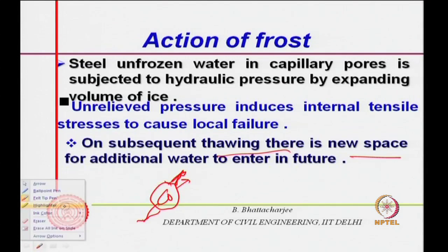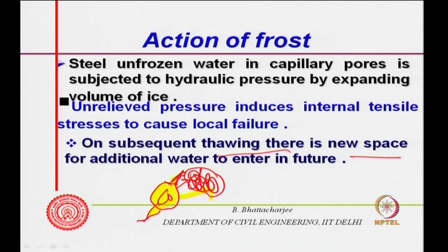Now, next time when water freezes, water will enter into this as well as into the new cracks, and freezing action will be there in these newly formed fissures or spaces again. So, in other words, this will exert more hydraulic pressure, because more pore space is available which is filled with ice. Some spaces which were not earlier filled by water now get filled up by water and can get frozen, and if they get frozen, that would exert pressure outward.